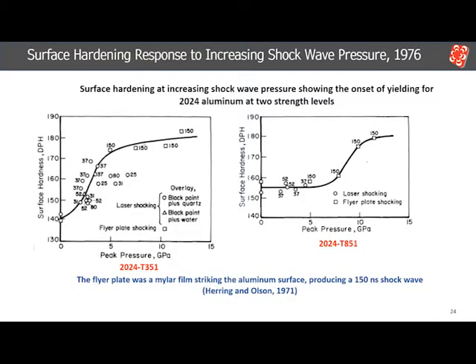In looking at work hardening of alloys by laser peening, most attention was given to 2024 aluminum. The surface hardness was measured with increasing power density to determine the pressure at which work hardening occurred. Black paint and quartz overlays were used for most of the shots. Two heat-treated conditions were investigated.